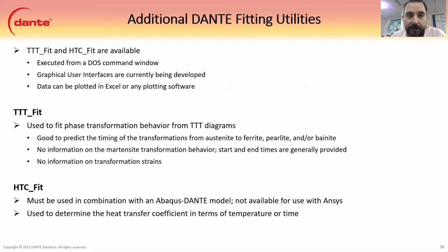They're really good for predicting the phase transformation timings of the diffusive phases, right, pearlite, ferrite, and bainite, but it doesn't offer any information as far as the Martensite transformation behavior, like the MS. Obviously, because of the nature of the TTT, it's an isothermal hold, and Martensite isn't included in that. So usually the Martensite start and end times, the MS, are provided, and you don't get any information about the transformation strains, which are really important as far as distortion prediction.